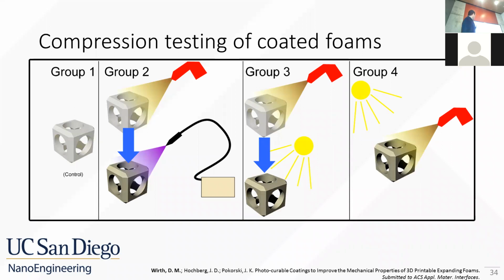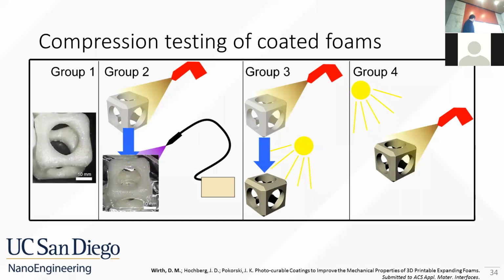We printed these, expanded them, and created 4 groups of samples. Group 1 was the baseline foam with no coating, the control sample. Group 2 was coated using the S100 resin and then cured using an artificial UV light source. Group 3 was coated and then cured using sunlight, and group 4 was sprayed in the sunlight.